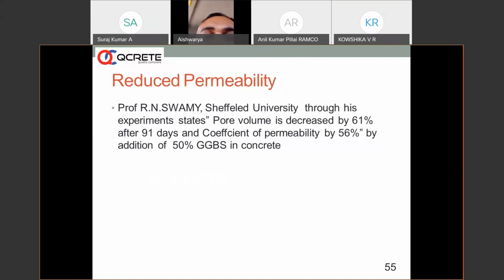R.N. Swamy from Sheffield University has done a lot of scientific research on blended concretes, and one of the important points established is that pore volume, that is porosity of concrete, capillary pores, etc., are decreased by 61% after 91 days, and coefficient of permeability is reduced by 56% when we are adding about 50% of GGBS. So this is important information when we are talking about the improvement of durability. There is a significant reduction in permeability, and hence a tremendous improvement in durability because of this reduction in permeability.